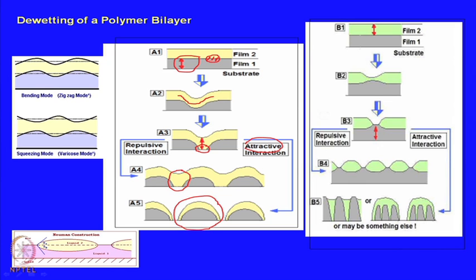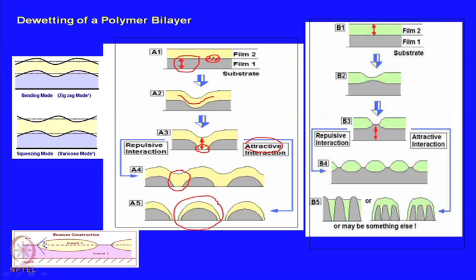So, in that relation of lambda, n, etc., the surface tension value gets replaced by the interfacial tension, which is 1 order smaller. So, lambda, n, etc., are all going to be reduced. So, you also achieve significant feature dimension miniaturization by using a bilayer.